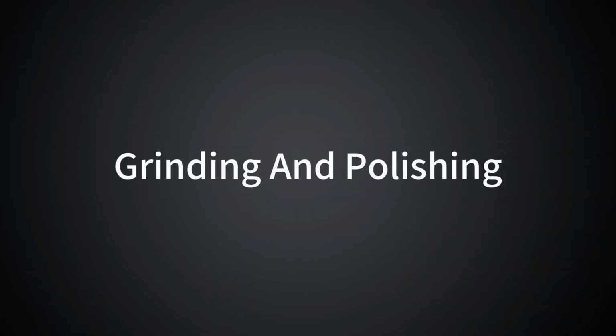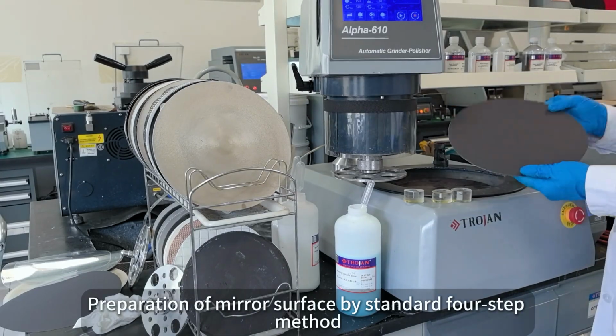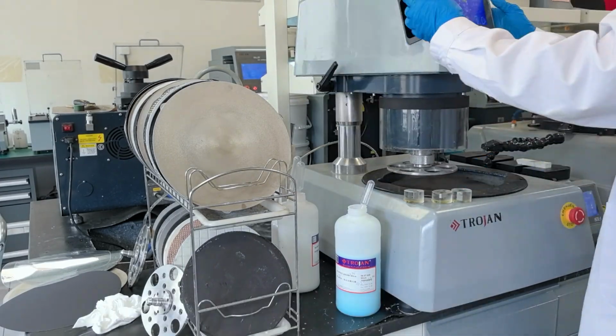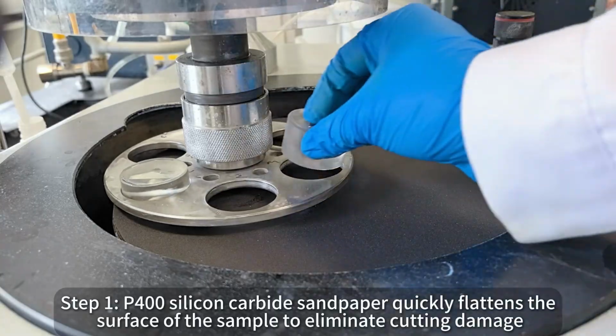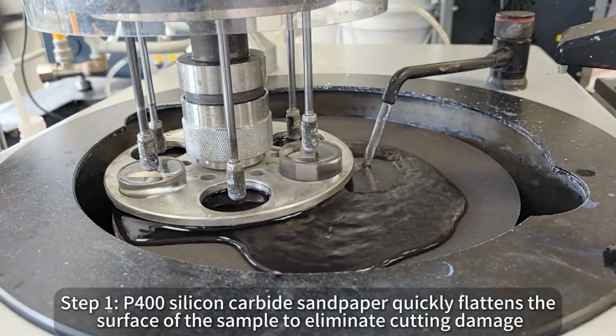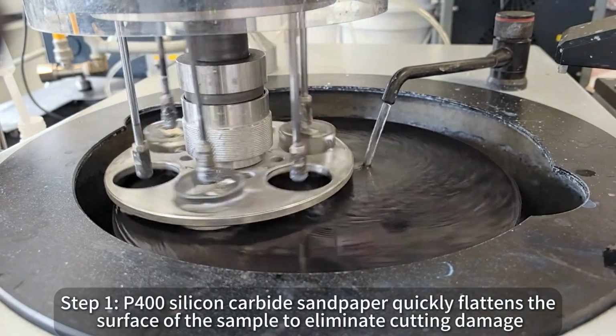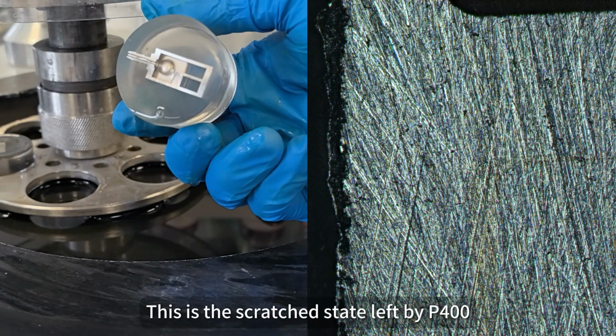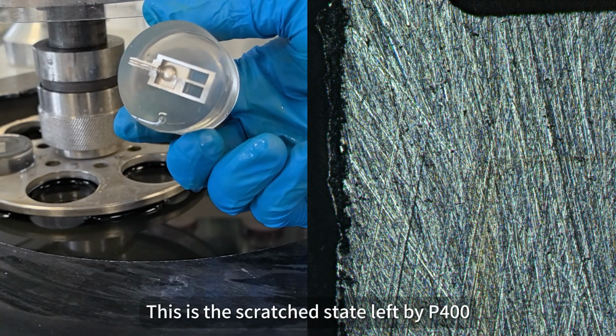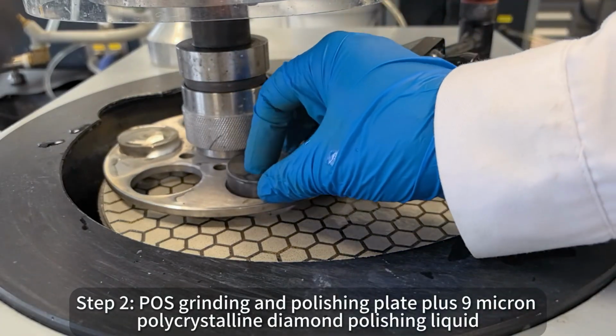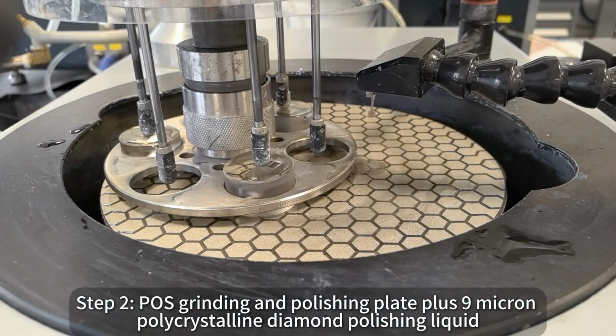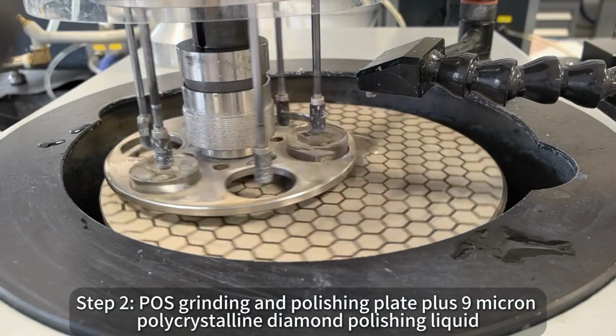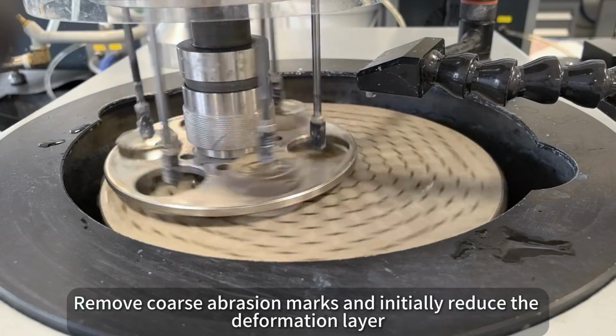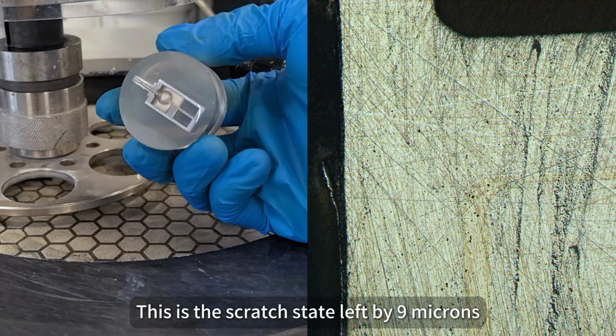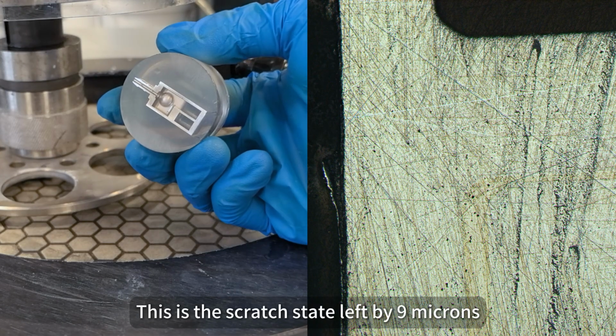Grinding and polishing. Preparation of a mirror surface by the standard 4-step method. Step 1. P400 silicon carbide sandpaper quickly flattens the surface of the sample to eliminate cutting damage. This is the scratched state left by 400 grit. Step 2. POS grinding and polishing plate and add 9-micron polycrystalline diamond polishing liquid. Remove coarse abrasion marks and initially reduce the deformation layer. This is the scratch state left by 9 microns.